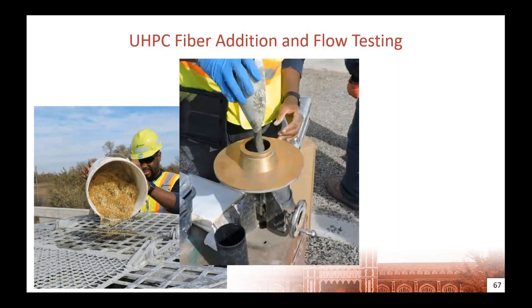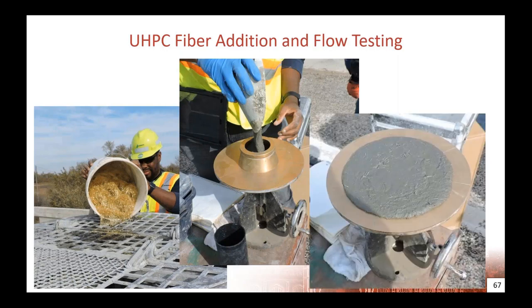After the fibers were added, they were allowed to mix for a few minutes, and then the QC test would run. The flowability test is similar to a mortar flow test, except they use the same drop table setup and the same cone. The difference is once the cone's lifted, it's only allowed to flow out over a certain amount of time instead of dropping the table, since it's such a fluid material.